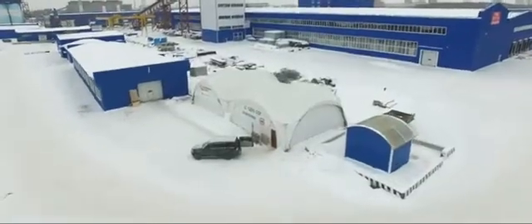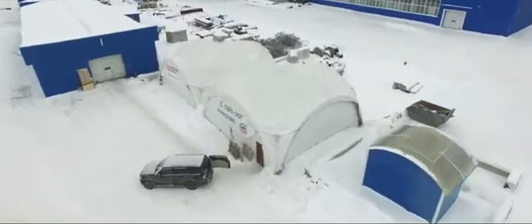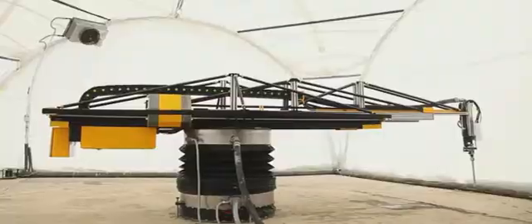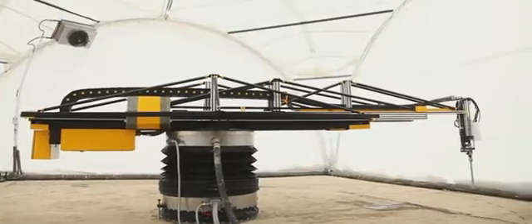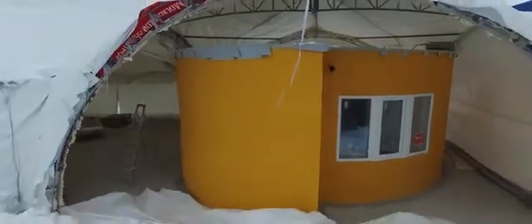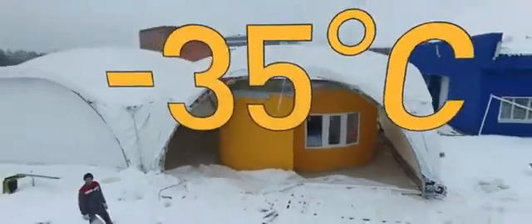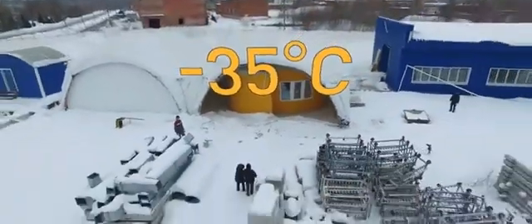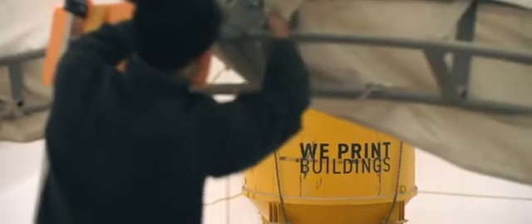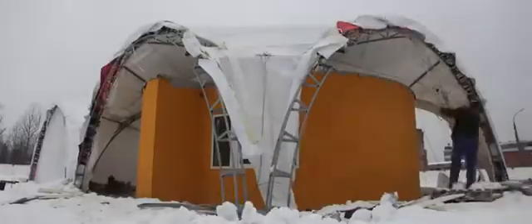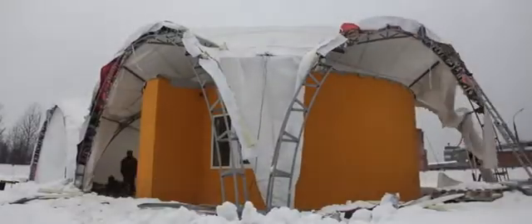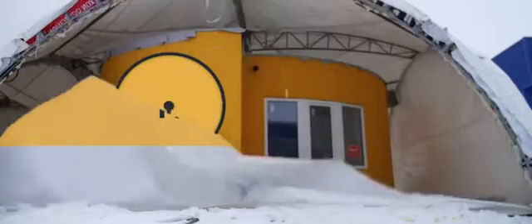Our project has been implemented at the coldest time of the year. Application of the concrete mixture that is used as the ink is possible at temperatures from 5 degrees Celsius above zero. The equipment can operate at temperatures as low as minus 35 degrees Celsius. However, the problem was easily solved by installing a protective tent, which maintained the required temperature. Time of printing amounted to 24 hours.